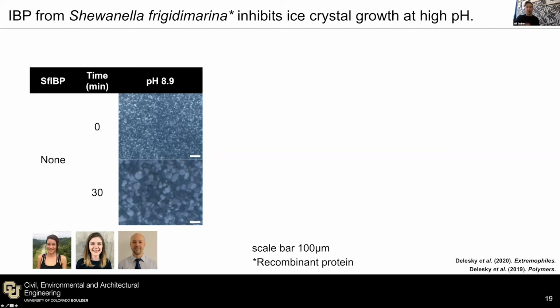So what we do is we take a drop of solution from a prescribed height, we flash freeze it to get a very thin monolayer of ice. We put it on a cold stage and we watch the ice crystals. And we can see the ice crystals at the very beginning, they're very small, and then over time grow into larger crystals. And so this is a sample, like I said, without any protein. So we see what we would expect to see, that larger crystals grow at the expense of smaller ones. And so this is just blank solutions without any protein.